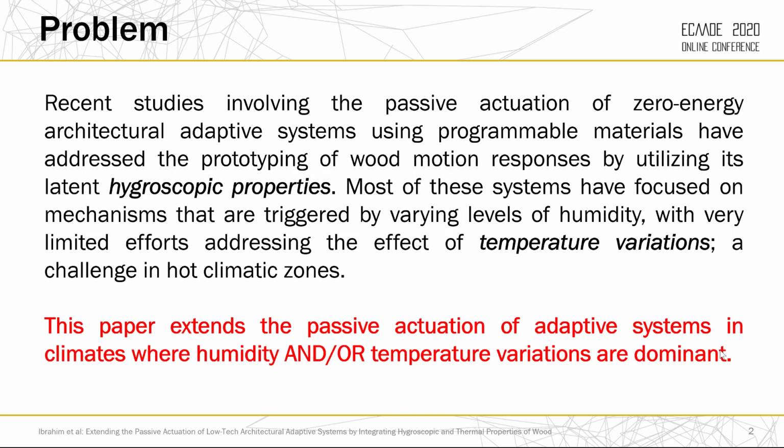estimate wood motion response. Hygroscopic properties of wood are related to its ability to absorb and hold water, causing swelling and shrinking upon water release. And wood, similar to other materials, undergoes physical transformations that are directly proportional to increased temperature. This is due to an increase in spacing between wood molecules as they improve the vibration magnitude at rising temperatures. These motions are typically evaluated as a coefficient of linear thermal expansion, which is a function of the relative change of proportion caused by change in temperature.